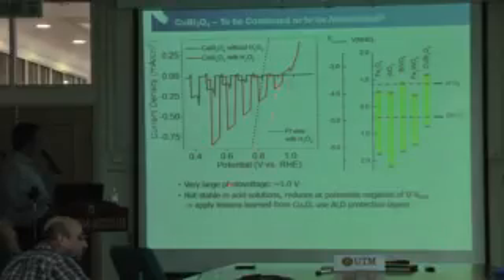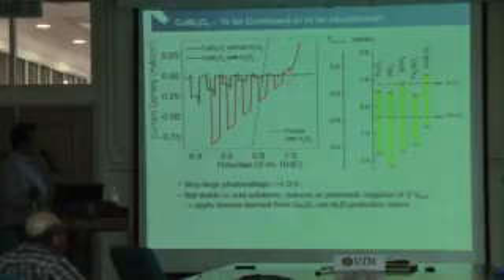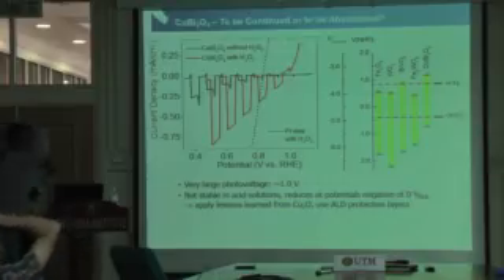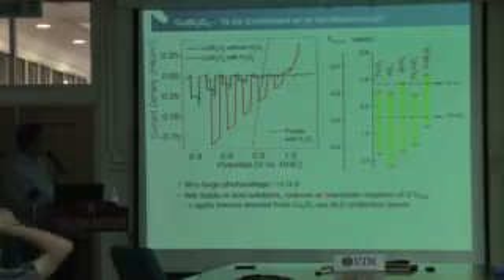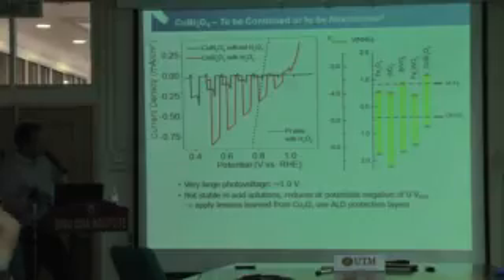But what's really interesting with this material is that it has a very large photovoltage. At about 1 volt over here, we're already seeing an onset of photocurrent, which means that you would be able to couple it with materials with non-optimized onset potential, such as silicon. For example, cuprous oxide starts way later at about 0.6 here, and p-type silicon only starts at about 0.5. So this onset potential of 1 volt is actually pretty exceptional.